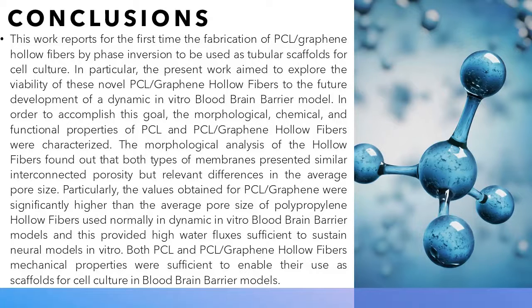The morphological analysis of the hollow fibers found out that both types of membranes presented similar interconnected porosity but relevant differences in the average pore size. Particularly, the values obtained for PCL graphene were significantly higher than the average pore size of the polypropylene hollow fibers used normally in dynamic in vitro blood-brain barrier models. And this provided high water fluxes sufficient to sustain neural models in vitro.